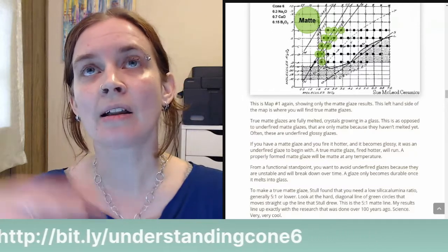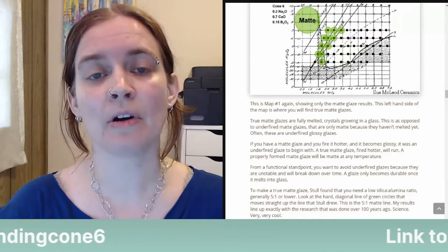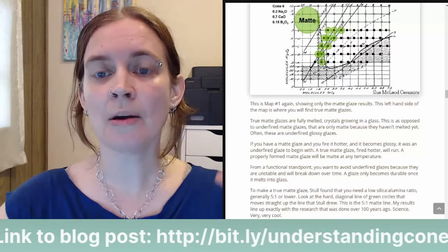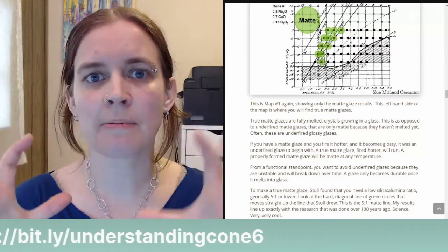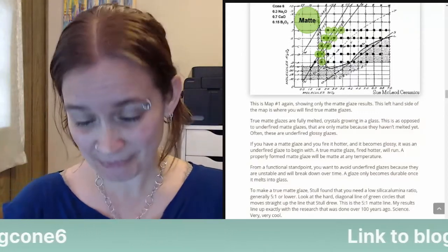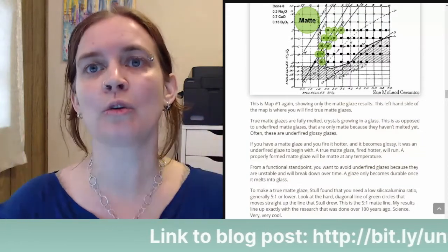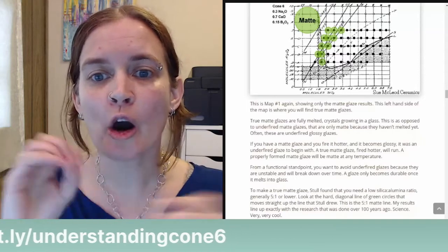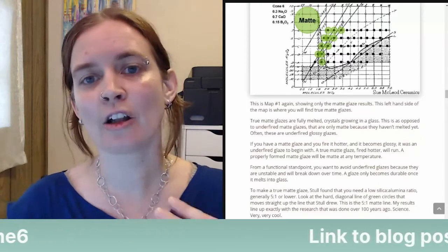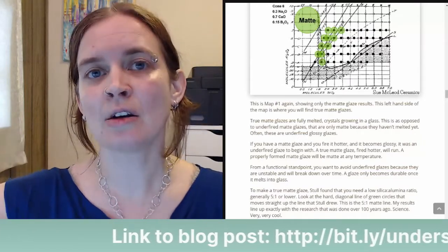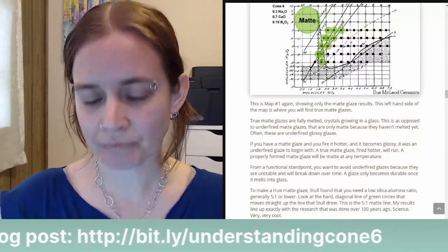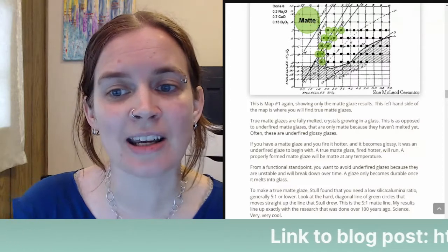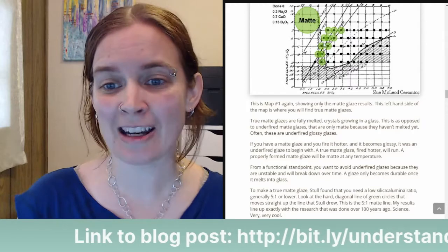It's when you have a glaze that is matte because of titanium, for example, that the cooling cycle really comes into effect. When we reach our target temperature, all of our glazes are liquids. They're really thick, syrupy liquids stuck to the sides of our pots, and they're all glossy and transparent. Then as the kiln cools, crystals will form to cause a matte surface. The difference between matte and glossy is that a matte glaze absorbs light and a glossy glaze reflects light. All of those teeny tiny crystals that form on the surface absorb the light rather than reflect it. So the cooling cycle isn't going to play a part in whether your glaze will be matte if it falls in this matte region of the Stull chart.